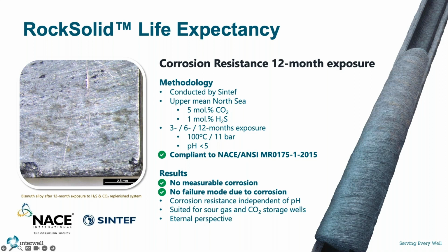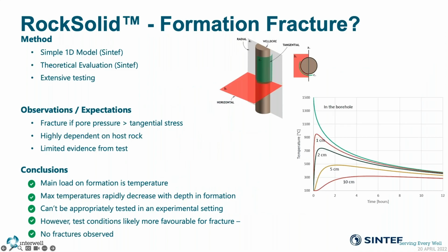Moving into the formation fracture potential slide. Next slide, please. So one of the common questions that we get asked is, as a result of the heat that we generate, do we create formation fractures at that setting depth? So for this, we again enlisted Sintef, a third-party organization, to conduct fracture testing. The findings were that fractures can't appropriately be tested in an experimental setting because we simply cannot create the overburden of a natural downhole environment.